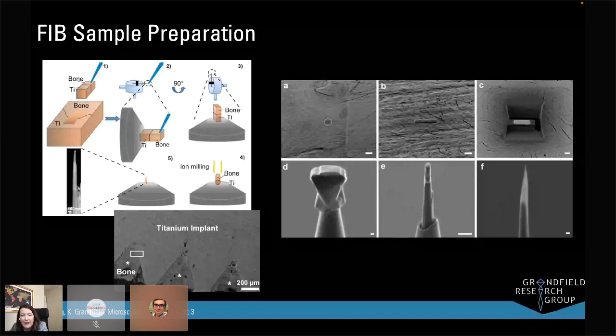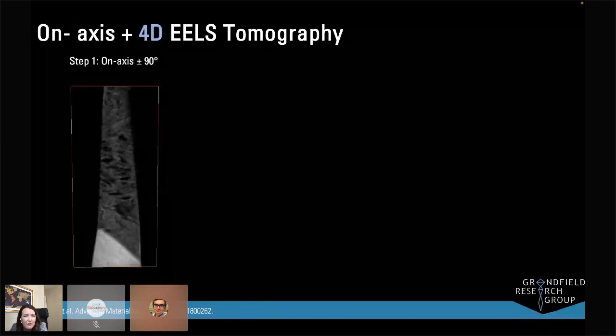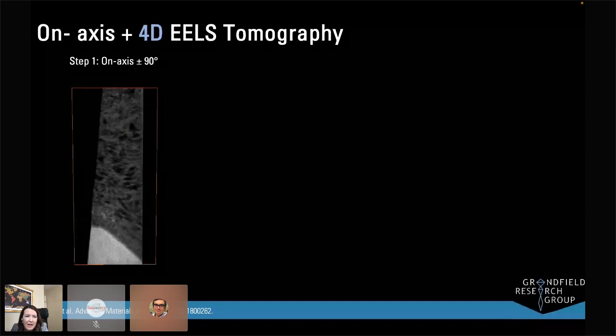So we have this needle, we put it back in the microscope, and we can take images and create a 3D volume. So here's the 3D volume shown here, our titanium implant on the bottom. We can see this nanostructured oxide on top of it and bone tissue above that.